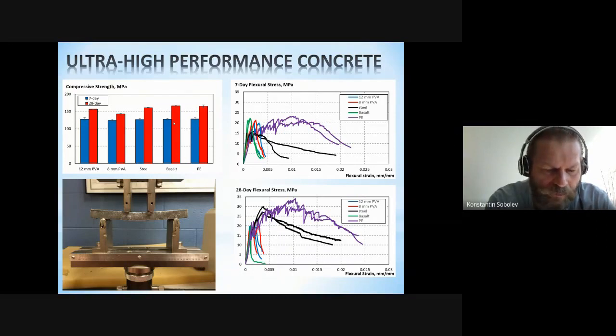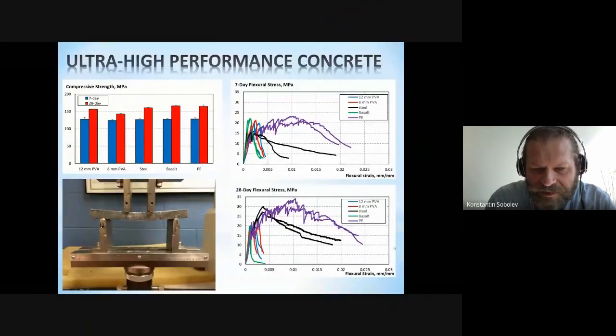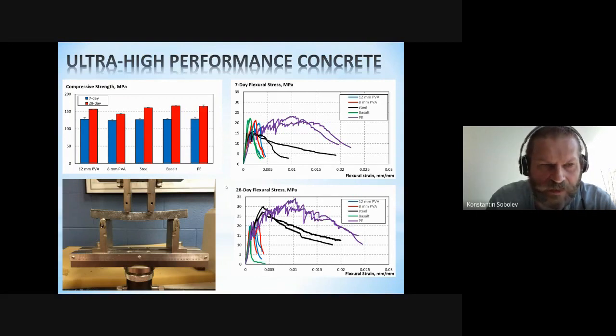Obviously, polyvinyl alcohol fibers are very popular, but if you look for really ductility, high density polyethylene fibers are the best, which you can see from the charts on your stress strain diagrams for 7 days and 28 days. Obviously, steel fibers are working extremely well if we compare them with polyvinyl alcohol fibers, but high density polyethylene really helps us to improve the response of this material and produce an outstanding product.